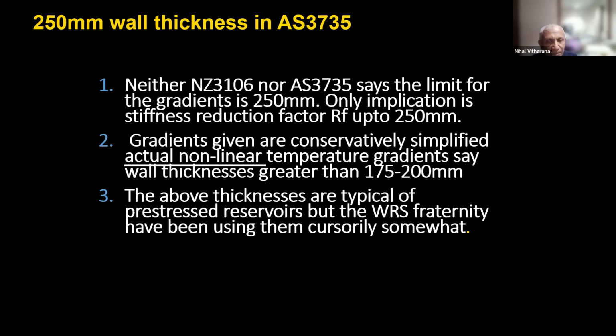As I said, similar thing. Then, I didn't want to make things complicated. When it comes to strain-induced loading, they are deformation dependent, or modulus dependent: E is Young's modulus, I is the inertia. Similarly, if you take something like an expanding steel bar and restrain it, the induced force is proportional to the axial area A and the E. So cracking of reinforced concrete relaxes the induced forces. That's what we call the stiffness reduction factor, RF, in the standards, and it only goes up to 250.